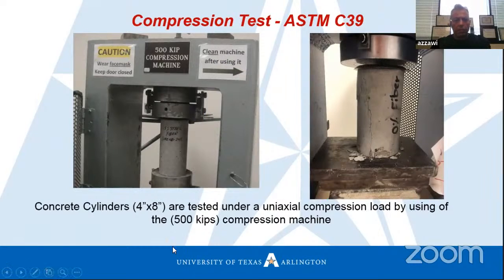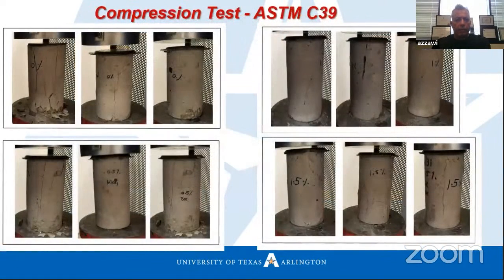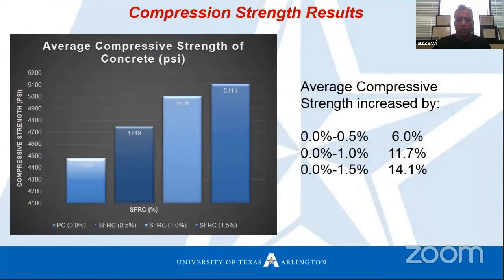These are the cylinders we prepared, 8 inches. These are the failures we have, as we see, with 0 fibers. We have cracks here. It's really noticeable. With 0.5%, we have failure, but we don't have that many cracks. And this is 1%. And for 1.5%, as we see, we don't have that many cracks. That's why steel fiber makes concrete behave in a ductile way instead of as a brittle material.